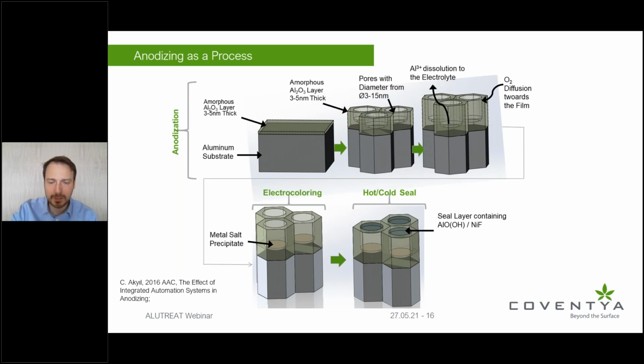And this porous structure is very beneficial, not that it is transparent, but the most important part of this porous structure is that you can use this as a template for several applications, even growing nanofibers, but in our case, for electrocoloring, you can use this to precipitate several metal salts in order to change the surface aspect or surface color.